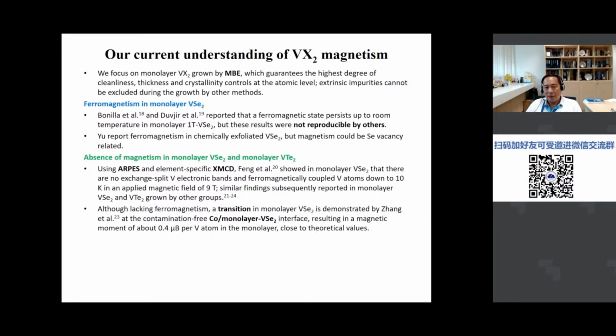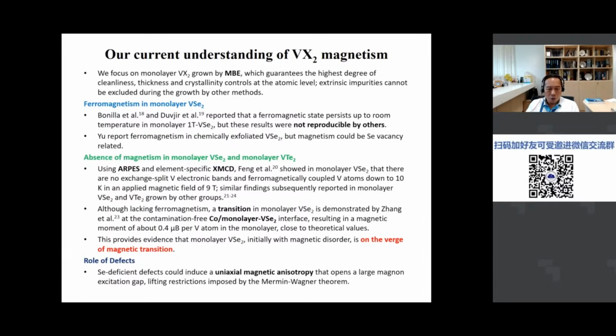But although they lack ferromagnetism, we can easily induce magnetism by proximity effects, for example in the cobalt VSe2 system, or by various other magnetic dopants as mentioned previously. So this provides evidence that the material VSe2 and other similar ones are on the verge of magnetic transition. And on the role of defects, our final study was to show that selenium deficient defects could induce a uniaxial magnetic anisotropy that could open up a large magnon gap, lifting the restrictions imposed by the Mermin-Wagner theorem. So this is our current understanding of this system.